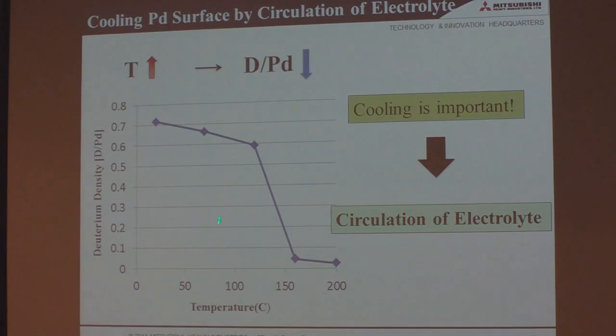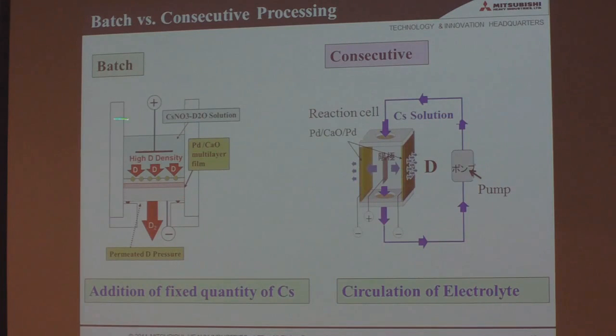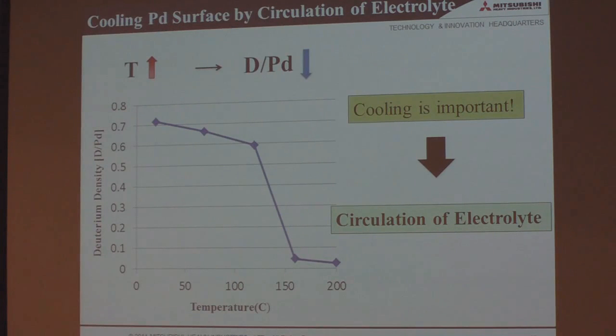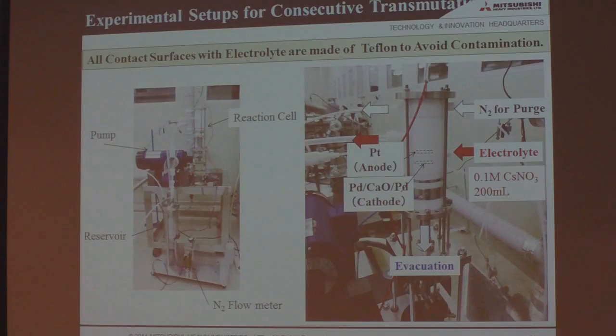This is the figure for the temperature and D by Pd relation. In this area, you know very well, I think, at one atmosphere. If we increase the temperature, palladium's D by Pd goes down. So temperature goes up, D by Pd goes down. So in the batch experiment case, we suppose that the surface temperature gets very high, so we should cool the surface by circulation of electrolyte. So we started this kind of experiment.